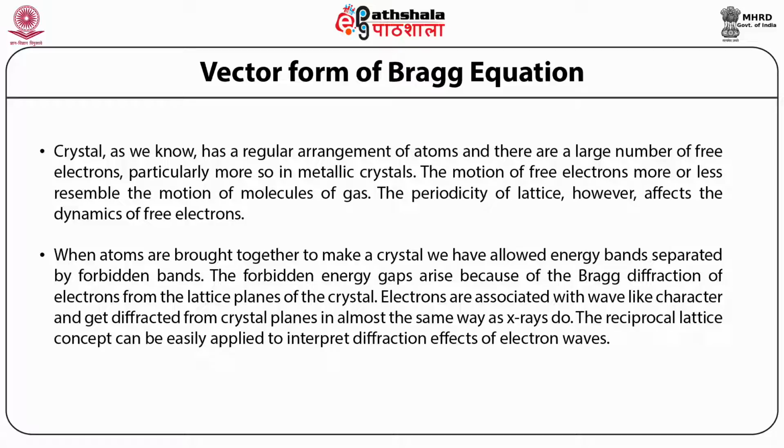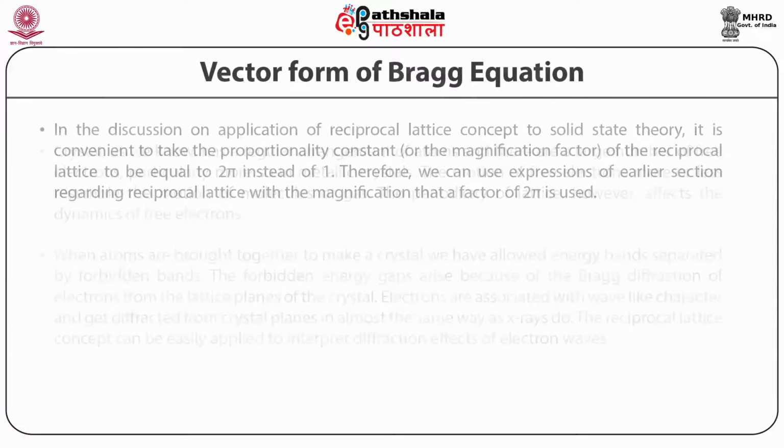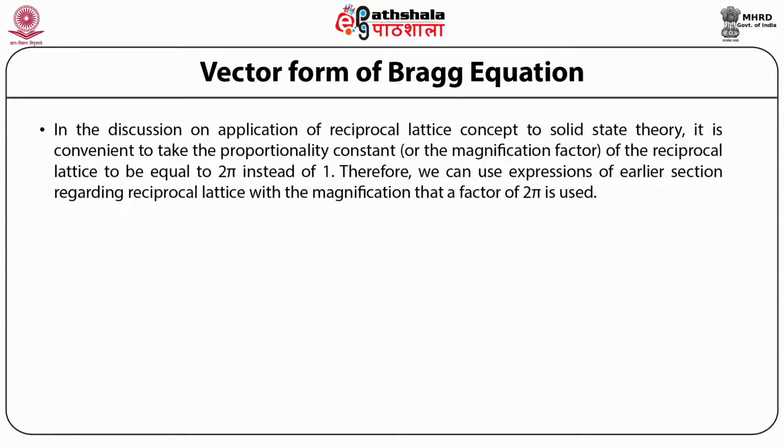Electrons are associated with wave-like character and get diffracted from crystal planes in almost the same way as X-rays do. The reciprocal lattice concept can be easily applied to interpret diffraction effects of electron waves. In the discussion on application of reciprocal lattice concept to solid-state theory, it is convenient to take the proportionality constant, or what we call the magnification factor, of the reciprocal lattice to be equal to 2 pi instead of 1.